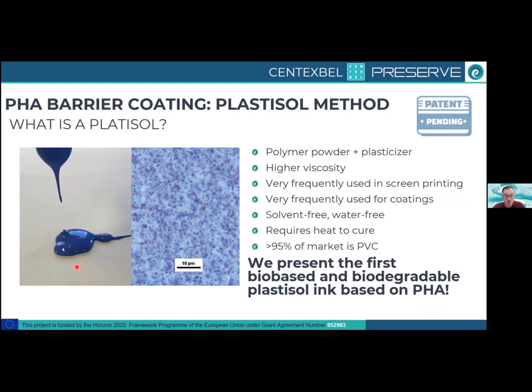PHA is used as a barrier coating using the plastisol method. Now, what is really a plastisol? You can make this by using a polymer powder and a plasticizer. Then you create a very high viscosity material that can be used in coatings and also in screen printing. Centexbel has a patent on this that also uses solvent-free and water-free materials. And it requires heat to cure this.